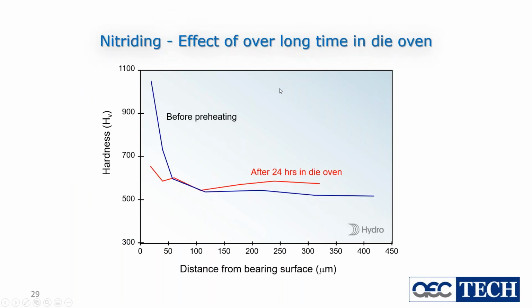Here is some data taken from hydro. And this blue line is the profile of a first-time nitrided die. Looks pretty good. If we did a surface indent on it, it's good and hard. We put it in a die oven for 24 hours, and this is what the profile looked like. We've lost all of this.